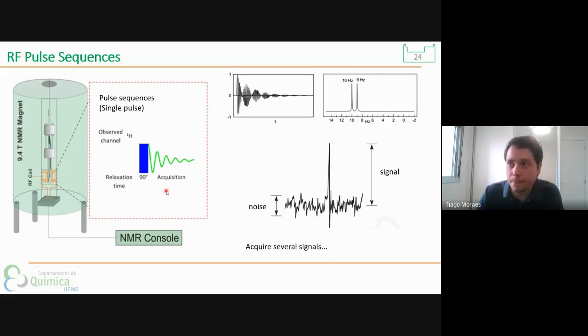Okay, then Marcus had talked to you about pulse sequences, but just to continue the story here, we have different pulse sequences that we can apply in your sample. The most simple one is just a single pulse of some degrees, where you have a relaxation time, you need to wait for the spins to relax. Then we apply the pulse and acquire a signal. Of course, you choose the channel, for example, for hydrogen. Then you obtain the free induction decay, as you can see here, and process the spectra.